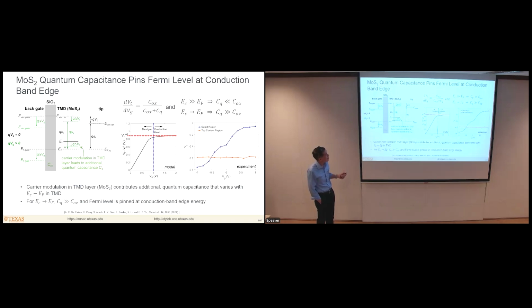All right. And if we construct a simple capacitive model for what should happen here, then at small gate bias voltages, where the conduction band edge is fairly far away from the Fermi level, there's not very much modulation of the charge in the MoS2 layer. And so the surface potential roughly tracks the gate voltage. But then for higher gate voltage, as the conduction band edge approaches the Fermi level, there's much more modulation of that charge. And what ends up happening is that because of the high density of states in the MoS2 layer, once the conduction band edge gets very close to the Fermi level, then they don't shift anymore. The Fermi level is pinned at the conduction band edge, and the surface potential no longer depends on the gate voltage. So that's what happens in this measurement.